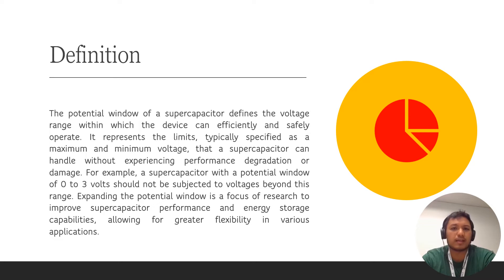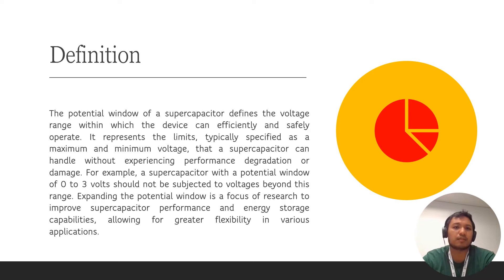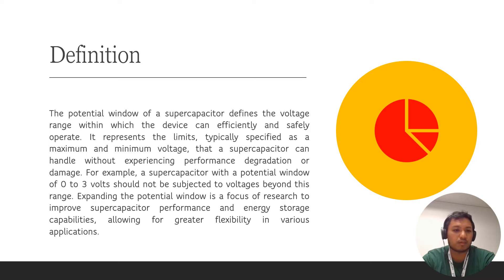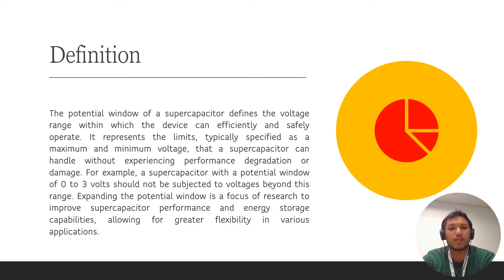For a supercapacitor, you should operate inside the potential window to avoid overcharging or over-depletion of your material. If you charge more than the potential window your device can achieve, it can damage your device. For example, if the window is 0 to 3 volts and you charge beyond 3 volts, your sample can crack, the material will be destroyed, and your specific capacity will decrease. So be careful when determining the potential window.